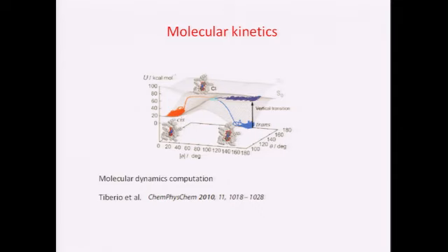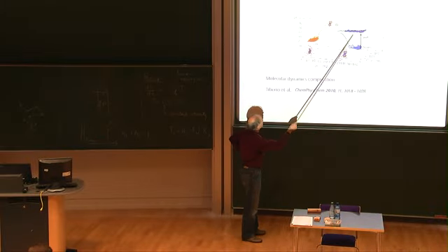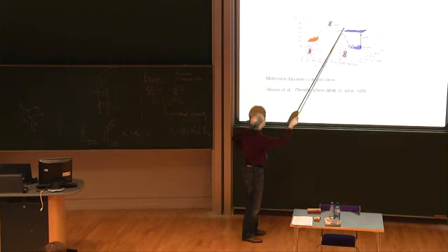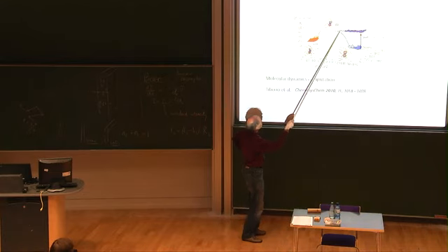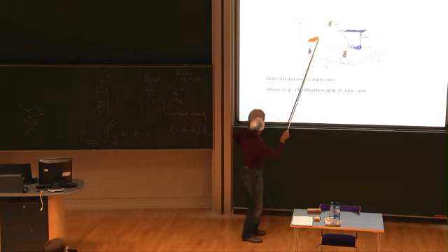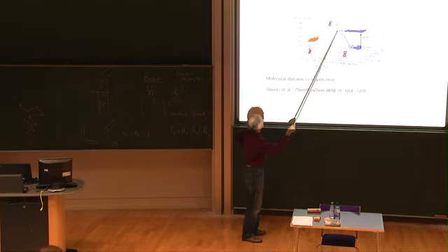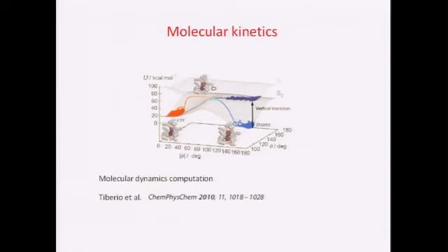And then this surface is a surface in terms of two vibrational degrees of freedom, which are important in this particular case. Obviously, there is a minimum in the excited state, which is different from the minimum of this vibronic band in the trans state, and it actually touches the maximum of this vibronic elementary ground state at some point. So when the system, by vibrations, transits to the minimum of the excited electronic state, it can go to either cis or trans. And of course, the reverse process is similar.